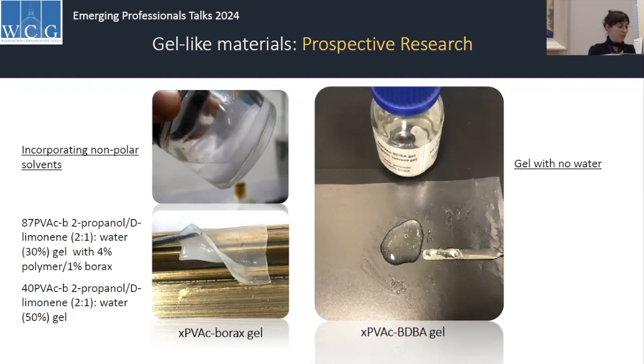However, something like D-limonene, which I wouldn't ordinarily use, but one of my paintings colleagues came to me looking to customise a gel for a painting cleaning challenge that they had. And so we came up with this, we tried it out because I saw that D-limonene was miscible with a hydroalcohol, so you could actually mix that with 2-propanol. And so if it's miscible with 2-propanol, maybe we could actually get it in the system. So I think that there's some interesting work that could be done in and around maybe having certain combinations of slightly non-polar solvents in these gel systems.